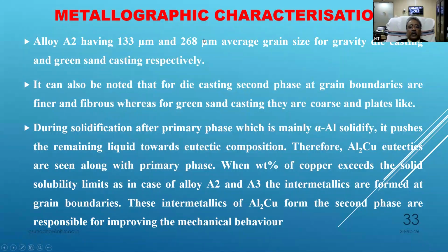It is also noted that in die casting, the second phase at the grain boundaries is finer and fibrous, whereas in green sand casting, it is coarse and plate-like. So you know that die casting gives a very high cooling rate, and along with the copper, it gives very fine grains and very compact structure, because that distance is very less.